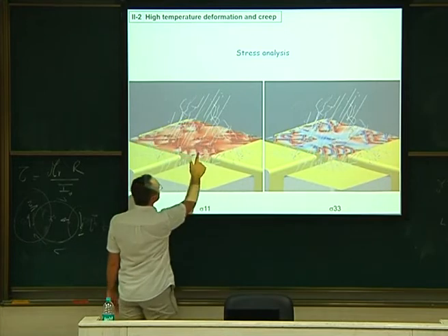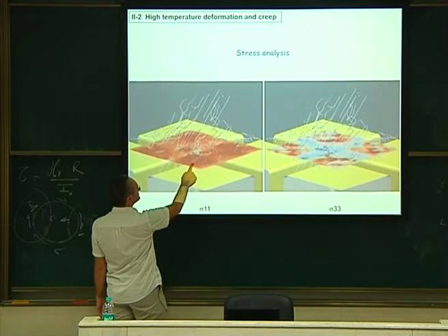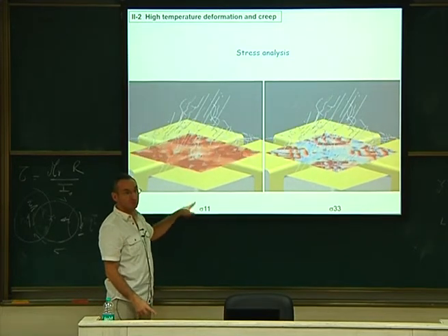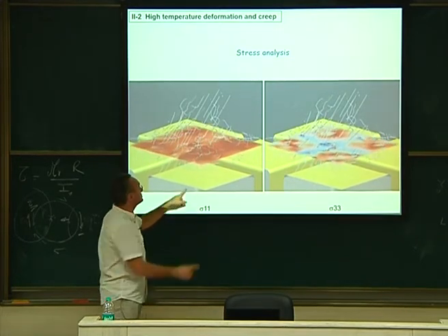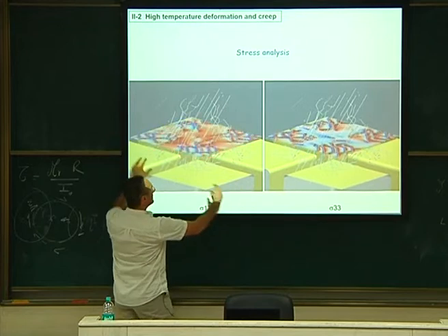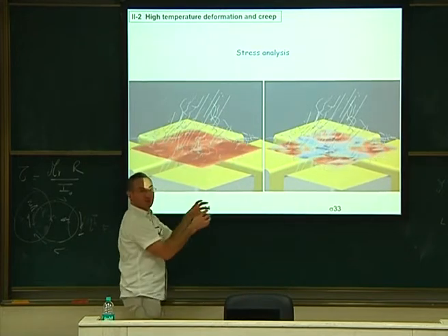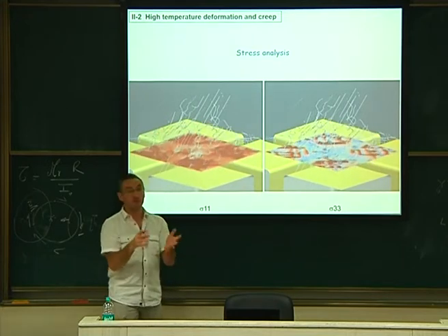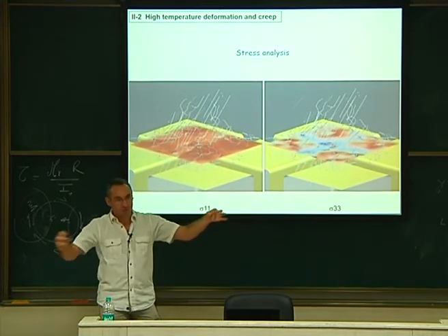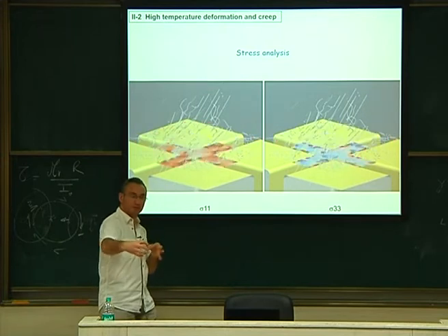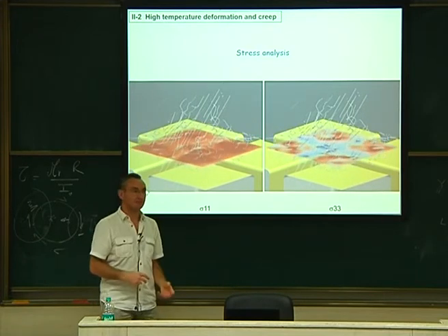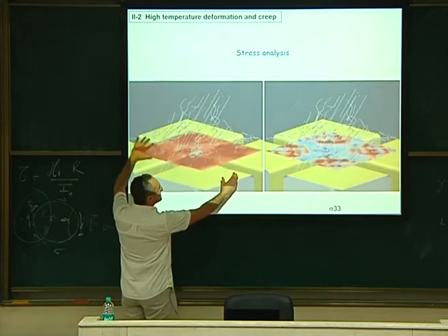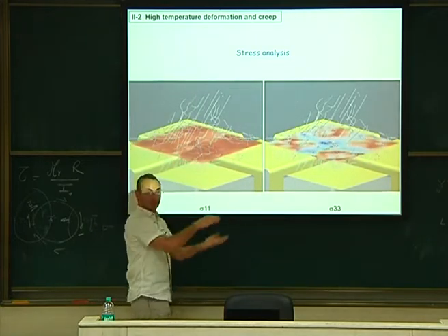But what we got is a sigma 11, which is huge. You have a huge sigma 11, and the same for sigma 22. Sigma 11 and sigma 22 are totally the same. So it means that you have some tension stress here, tension stress there, and because of this tension, you have a shrinkage. It's just because of the Poisson effect. You are expanding a lot on 11 and 22, and this contracts on ZZ, on 33. This is the origin of this contraction. Just because of the big stress along 11 and 22, that will shrink your specimen.